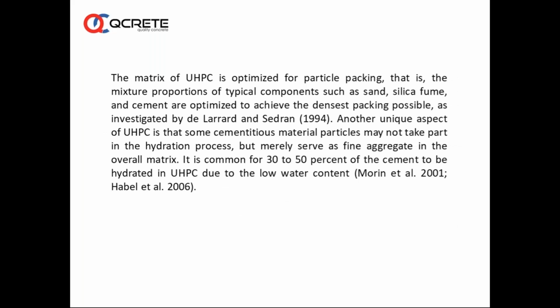The matrix of UHPC is optimized for particle packing, that is, the mixture proportions of typical components such as sand, silica fume, and cement are optimized to achieve the densest packing possible, as investigated by de Larrard and Sedran. Another unique aspect of UHPC is that some cementitious particles may not take part in the hydration process, but merely serve as fine aggregate in the overall matrix. It is common for 30 to 50% of the cement to be hydrated in UHPC due to the lower water content. So, due to the lower amount of water available, as we are using a very low water cement ratio, some of the cementitious products may remain unreacted in the body of concrete, and they can remain forever in that state.